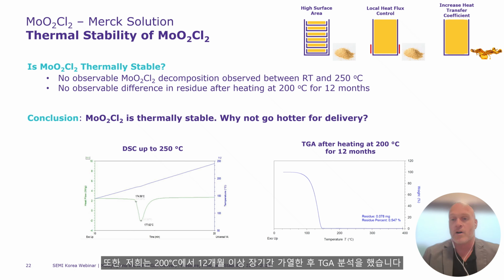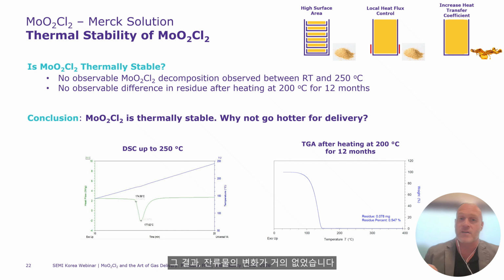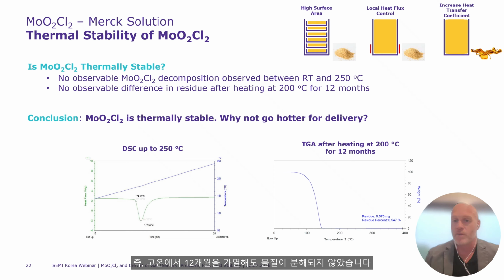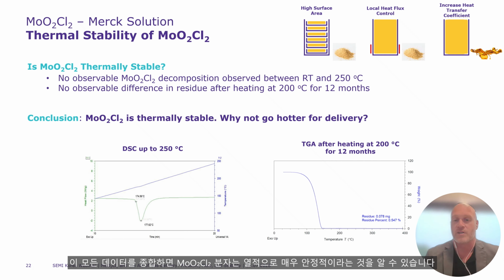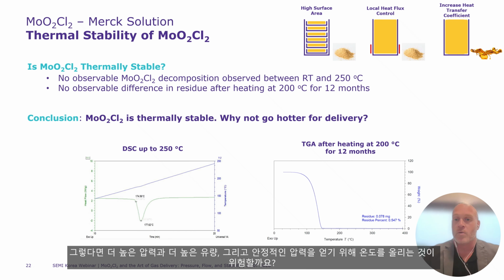And then furthermore, we've heated material for 200 degrees for long periods of time, 12 months and longer. And then we take TGA before and after. And so basically the change in residue, there's no change in residue after 12 months of heating at high temperatures. So both of these collectively show that the molecule itself, the fundamental molecule itself, moly dichloride, is thermally stable. And so what's the risk of going hotter to get to higher pressures, higher flows, and stable pressures throughout?